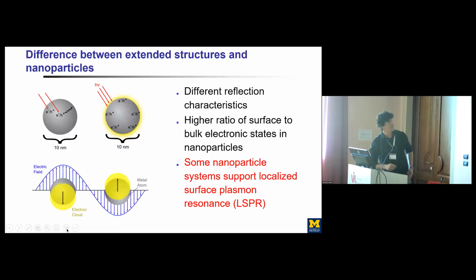Another very important difference is that some of these nanoparticles can support something called localized surface plasmon resonance. This is basically a condition in which you have a natural oscillation of the electron cloud in the nanoparticle, and that electron cloud is interacting with the electric field of a photon that's hitting the nanoparticle. When they're in sync, you get a resonant condition. So what it essentially means is that you can put lots of energy in your nanoparticle, and you can put them in these surface plasmon resonance states.